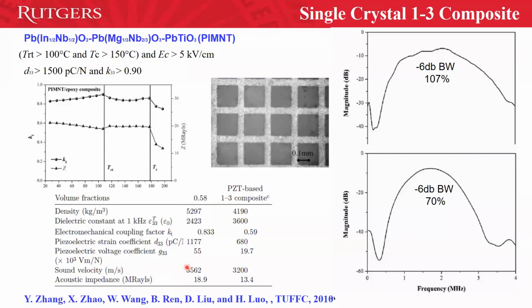This is another work, single crystal made with Haosu Luo and his group, on lead indium niobate, lead magnesium niobate, lead titanate single crystal 1-3 type composites. Here is the single crystal, and these are the polymer. The bandwidth of these composites is about 107%, this is the minus 6 dB bandwidth. Again, that was another encouragement, really for using these in medical ultrasound applications.